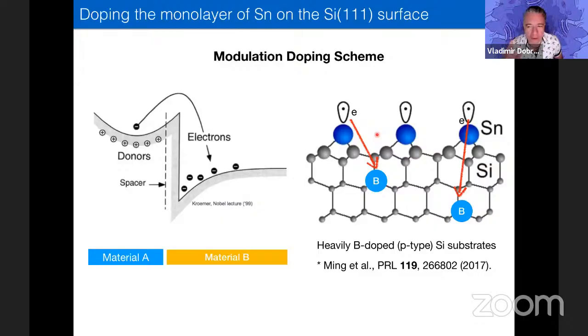Can I just ask another clarifying question? Absolutely, yeah, no problem. When you put dopants on silicon like phosphorus, you get orbitals which are very large compared to the silicon lattice. How big is the tin orbital in units of the silicon lattice? So the tin orbitals here are actually quite confined and oriented perpendicular to the surface. The boron orbitals from the dopants, I'd actually have to go back and double check. I don't know. Yeah, the Bohr radius is like 20 angstroms.